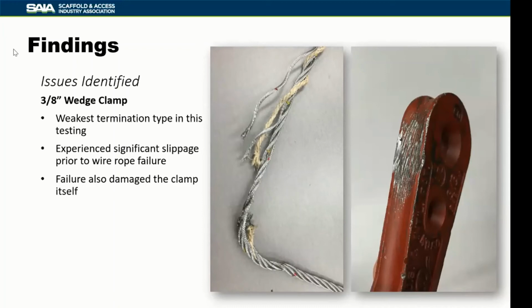So for anyone that may be using a 3/8 inch wedge clamp, I understand that these are significantly higher loads than what you would ever experience in the field under normal operations. But there is a possibility under abnormal operations that significantly higher loads can be generated by hoist on the wire rope. And we would never want to get into a situation where we actually pull the wedge through its housing because we're using an oversized wedge clamp.